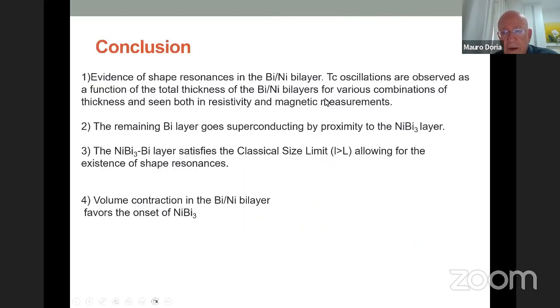In conclusion, evidence of shape resonances: TC oscillations are observed as a function of the total thickness for various combinations of thickness, and seen in both resistivity and magnetic measurements as well. The remaining bismuth layer goes superconducting by proximity. This nickel bismuth 3 satisfies the classical size limits, meaning that the mean free path is larger than or similar to the thickness of the system. And we observe the volume contraction that favors the onset of nickel bismuth 3.